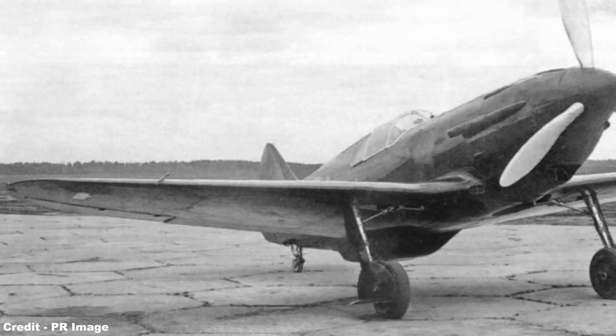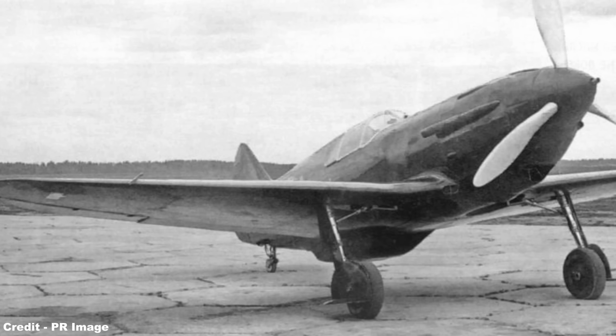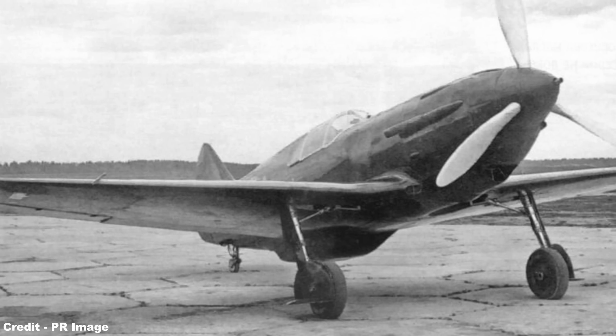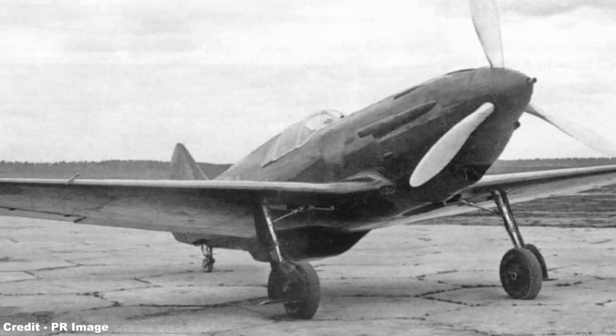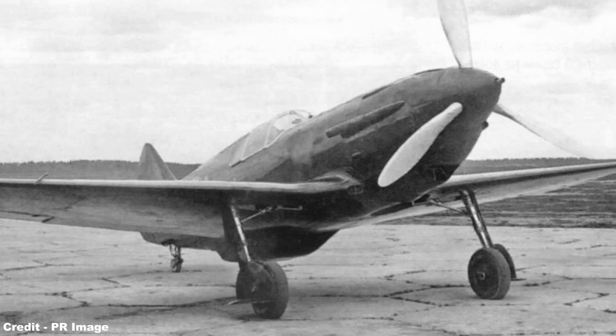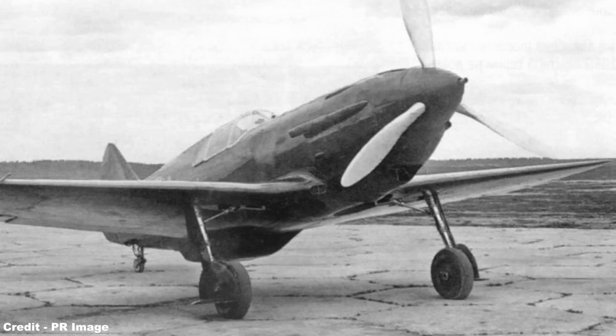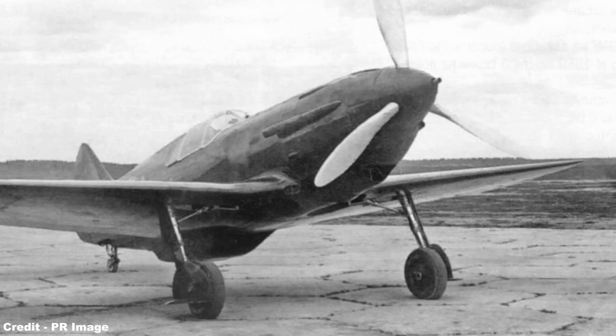In this climate of urgency and constraint, design work began in 1939 on a new fighter aircraft under the direction of Semyon Lavochkin, Vladimir Gorbunov, and Mikhail Gudkov, with their solution being the I-301 prototype, an aircraft constructed predominantly from an innovative laminated wood product known as Delta Wood. This material consisted of thin veneers of birch or pine bonded together with a synthetic resin and hardened under heat and pressure, offering surprisingly high tensile strength, decent durability, and was both rot-resistant and fire retardant. Crucially, it could be produced without drawing on the overstretched reserves of light alloys, making it a pragmatic choice for wartime production.